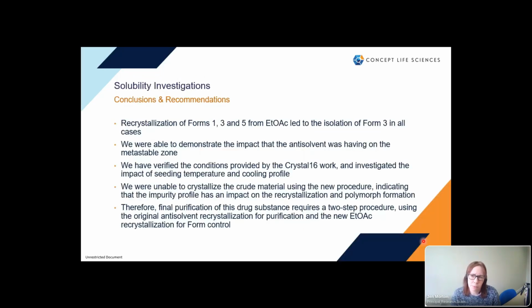Okay, so to conclude that section, we have recrystallized forms 1, 3, and 5 from ethyl acetate. And that's led to the isolation of form 3 in all cases. We did a little bit of work to try and look at the impact that the antisolvent was having on the metastable zone. We have verified the conditions provided by the Crystal16 work, and we've investigated seeding temperature and cooling profile. We were not able to crystallize the crude material using the new procedure, leading us to conclude that impurity profile is critical. And therefore, we would say that the final purification of this drug substance is going to require a 2-step procedure using the original antisolvent recrystallization for purification and then the new ethyl acetate recrystallization for form control.